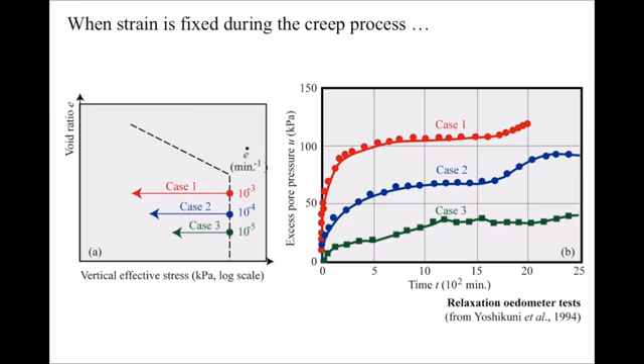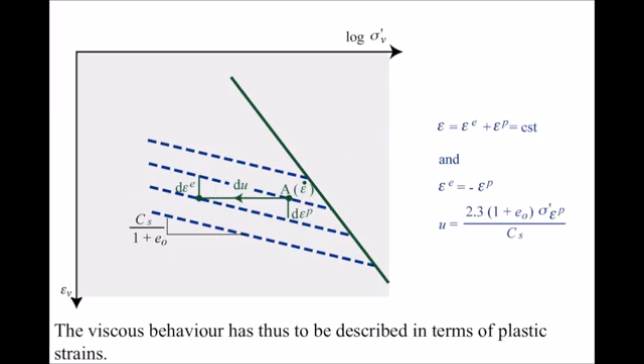During this test with time, in fact, the pore pressure increases. And so the effective stress is decreasing. And the explanation is given here. If we have soil at a point such as A here, in fact, the plastic strain has a tendency to creep. The plastic strain has a tendency to increase and so to go here.